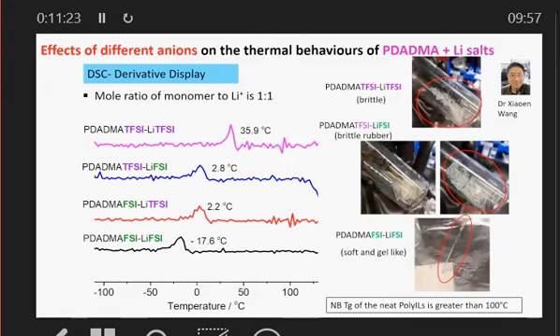When we have the homoanion FSI, FSI, we see Tg decreases. So in this case, those of you who know about polymer electrolytes from PEO, for example, polycarbonates, what we find usually is as we add more and more salt, the Tg goes up and the conductivity goes down. In these systems, as you add more and more salt, the Tg goes down and the conductivity goes up to a maximum, to a point, which we'll talk about in a moment. Based on this work, and I note here that the polyIL itself has a Tg that's around 100 or more than 100. Very hard to measure the Tg of this particular system by DSC, and I'll talk about that a bit later on as well.